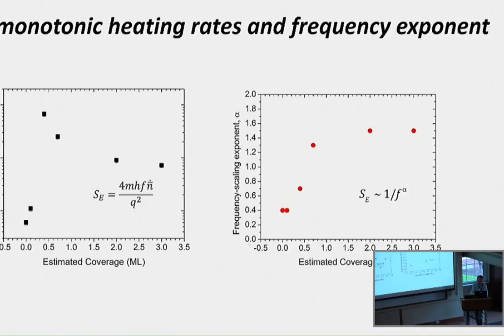Okay. So then, another thing that doesn't make sense is when you incrementally clean the trap and measure a heating rate after removing some of the stuff for 5 minutes at a time, measure heating rate, hit it again, measure heating rate. So the coverage is going down incrementally.